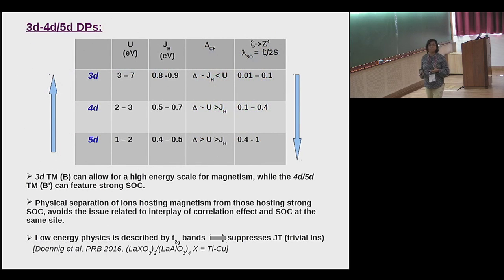Now, taking this compound, since instead of one site you now have two different sites, B and B prime, you can afford to put a 3d transition metal at the B site and a 4d or 5d transition metal at the B prime site. The conventional knowledge is that the correlation effect is strong and weakens as you move from 3d to 4d to 5d, but the spin-orbit coupling strengthens as you move from 3d to 4d to 5d. So the idea is the following: since I have a physical separation between B and B prime, one of them, where I put a 3d transition metal, can allow for a high energy scale for magnetism, while the 4d or 5d can feature strong spin-orbit coupling.